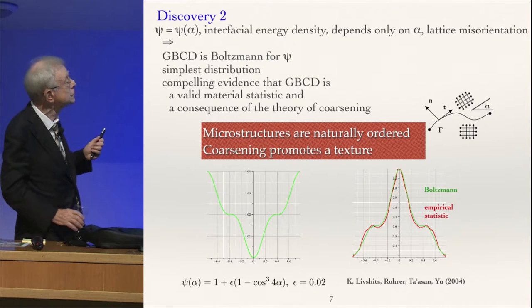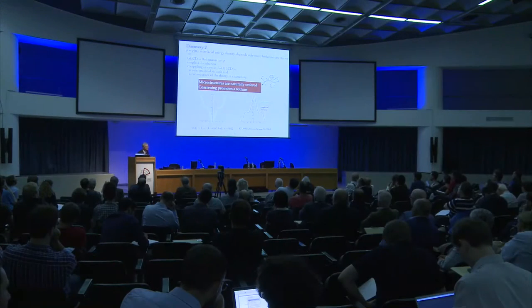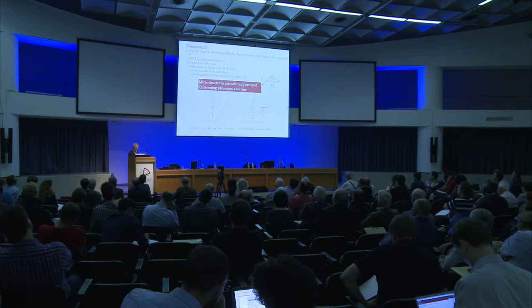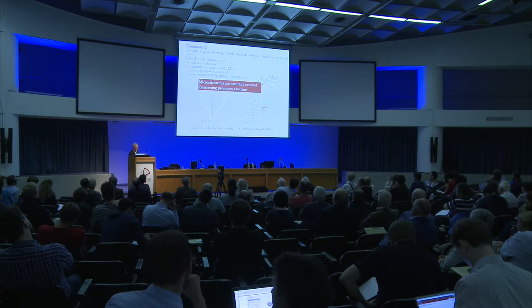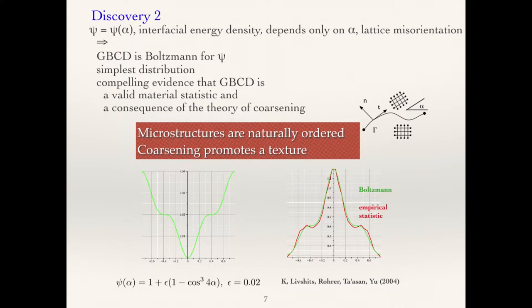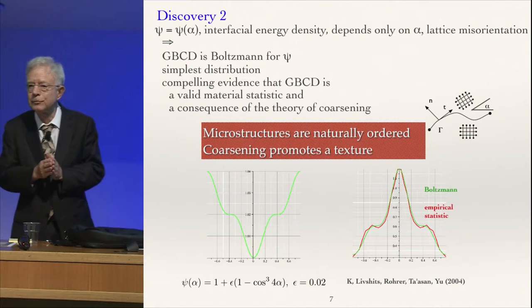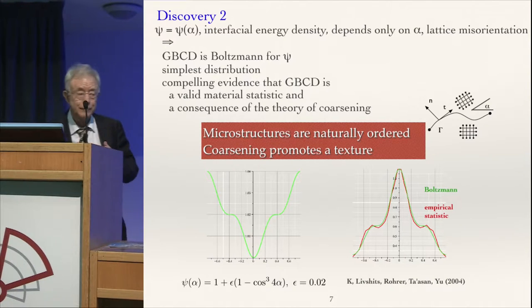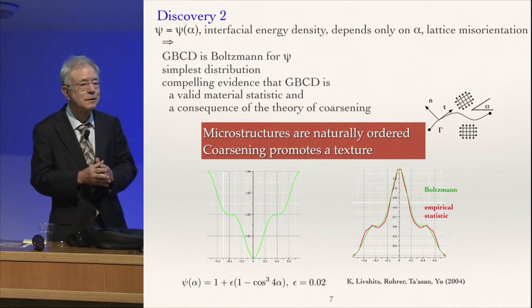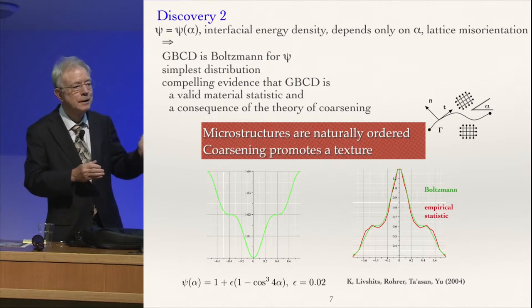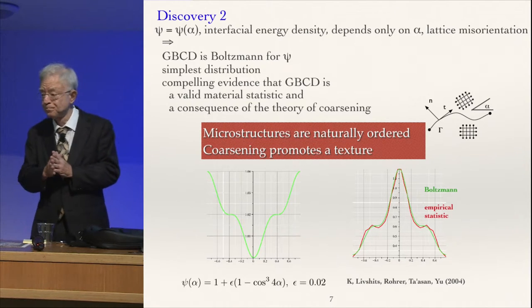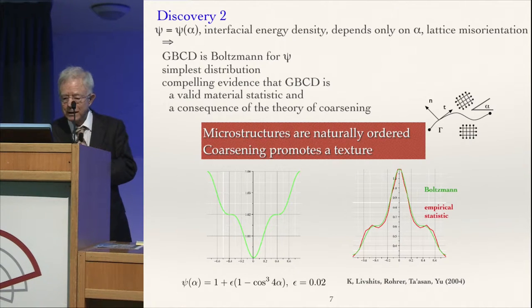And the second discovery is that if we choose some sort of artificial situation where the prescribed interfacial energy depends only on the lattice misorientation and not on the geometric character, on the normal or anything, then the GBCD is always a Boltzmann distribution. This is the simplest possible distribution you can imagine, which is no distribution whatever. So this is compelling evidence that this GBCD, which is a product of curvature-driven growth or is measured in the material, is actually a material property. It's a valid statistic and a consequence of the theory of coarsening.